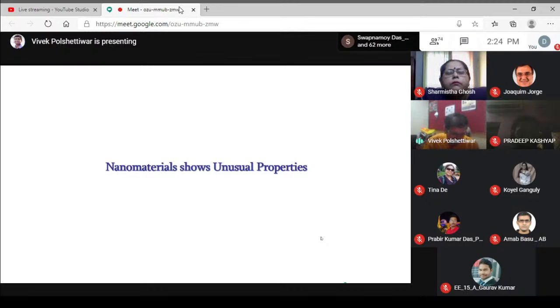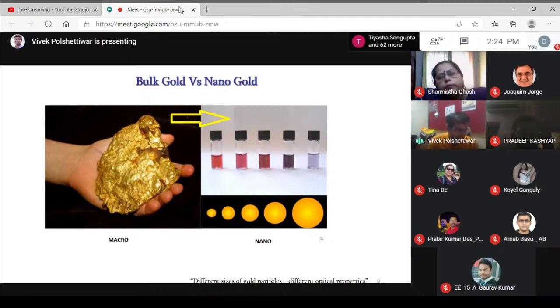Now it's not about the scale, but it's about that when you transform the bulk material, the material that you see around, into the nanoscale, they start showing unusual properties. For example, we know the gold, the jewelry and everything that we wear, those are yellow shiny colored. Why? Because the gold is metallic. The electron cloud on the gold surface reflects most of the light except a small portion of the blue light, and that's why it's yellow in color. Whereas as soon as you convert that bulk gold into very small nanoparticles of different particle sizes, based on the size, the electron cloud which was reflecting the light, now at a nanoscale starts oscillating with the electromagnetic field of the light. It's not reflecting, but it's oscillating, and at one particular wavelength there is a resonance. We call it a surface plasmon resonance, and that gives you different colors of the gold. So you can make gold of a different color.